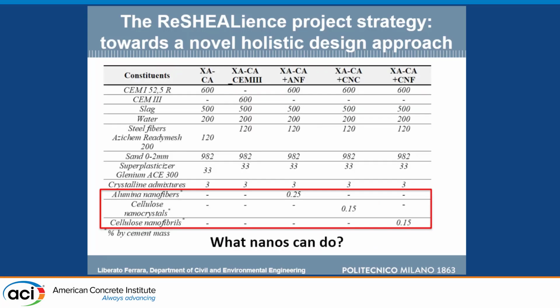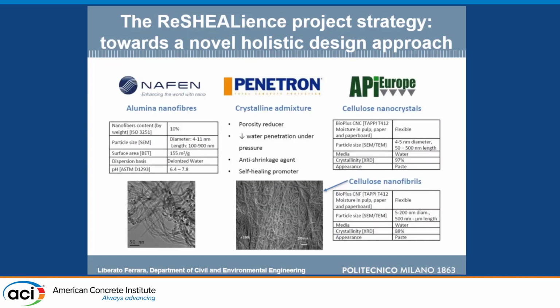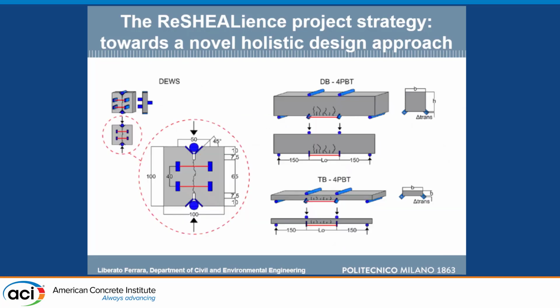Then, as I said, we wanted to strengthen the durability in the cracked state. We wanted to enhance the self-healing capacity, and we investigated the use of different kind of nanomaterials: alumina nanofibers, cellulose nanofibrils, and cellulose nanocrystals. You can see here some of the characteristics of the materials we used. For the nanofibers, we had lengths between 100 and 900 nanometers and diameters in the range of 10 nanometers. Similar dimensions, a little bit shorter, but the diameter was still in tens of nanometers for the nanocrystals and the nanofibrils. We characterized the mechanical performance of the material through bending tests and indirect tension tests.